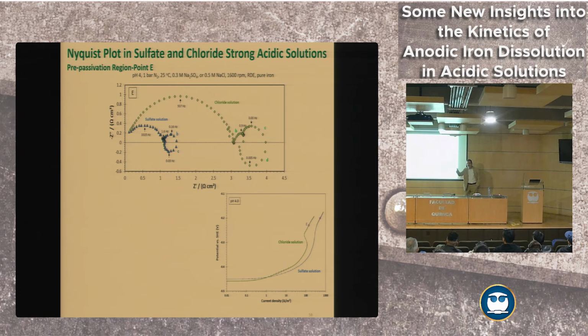It may prevent passivation. If we did this in stagnant conditions, it may have passivated here right away because you build up the concentrations of species and it forms some kind of a surface there. So another reason why we work pretty high is to avoid that. We did not want passivation. We wanted to understand not even what happens here, but what happens down there, because this is where our cathodic reactions are. This is where corrosion is. The rest up here was more to understand what happens above, but up here I really don't care. So that's why we focus on the active dissolution region, so that we do not have the precipitation.